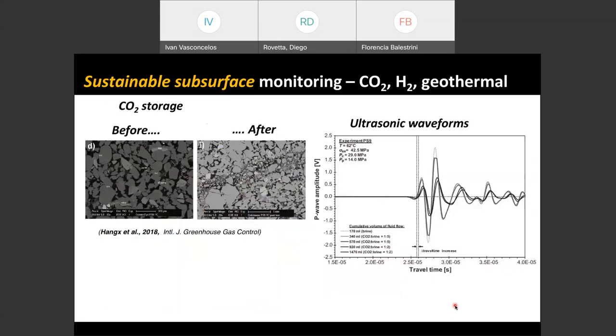What about CO2 sequestration? Well, that was well known in CO2 sequestration that CO2, of course, replaces whatever fluid is in the pores. Usually it's brine. So we already have a fluid replacement phenomenon happening, but it can also react with the microstructure. So here you see from my colleague Suzanne Hangx, two examples of the microstructure before and after CO2 sequestration. Note that the picture after is about 2 times the scale of the picture before. So if you see here, this is 500 micrometers, this is about a millimeter. So think that this picture here is about half of this picture here in terms of scale. So clearly the microstructure has changed.